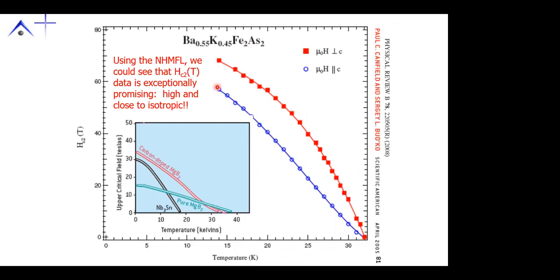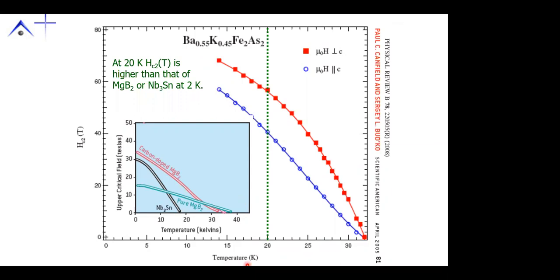And if we remember that 20 Kelvin was a big deal for MgB2, here, if we look at 20 Kelvin, the lower HC2 is in excess of 40 Tesla. That's higher than what any of these guys get at base temperature. So it immediately indicates that these have the possibility of being practical superconductors themselves.